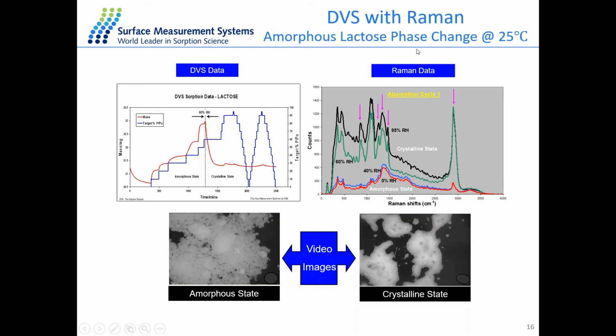Another option with the accessories is that we can integrate Raman spectroscopy with our DVS system, so that we can take Raman spectra at the end of each humidity step. In that case, we can get both the Raman spectra and the DVS data at the same time. For example, here the example is an amorphous lactose sample. We did the water sorption experiment at 25 degrees. The blue line indicates the partial pressure of each step. We increase from 0 to 95% RH with 10% steps. And the red line is the change of mass for the sample.